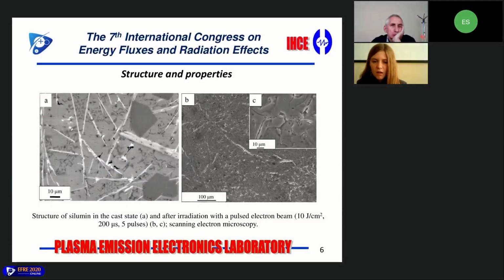So, the structure of the initial specimens consists of grains of aluminum-based solid solution containing silicon and other alloying elements, grains of lamellar aluminum-silicon eutectic, and precipitates of intermetallic compounds and silicon. The size of silicon varies from several to several tens of micrometers. You can see silicon is here, and intermetallic compounds is here.